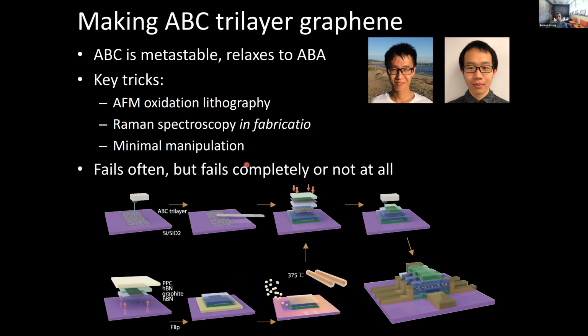But if you tried to make that a uniform system, you would end up with a Bernal stacking, because that is the actual structural ground state of a bilayer, and of a trilayer also. So this allows you to actually stabilize a metastable and uniform state, and that actually turns out to be a feature more than a bug.